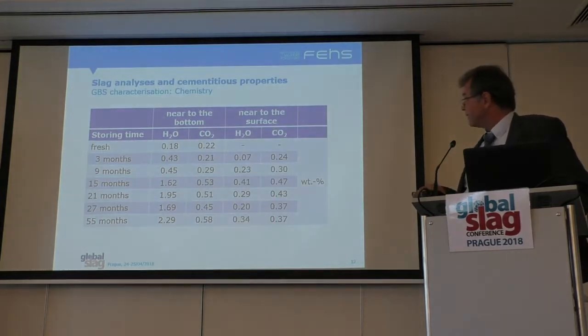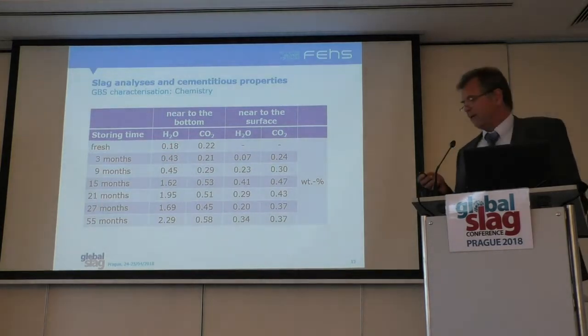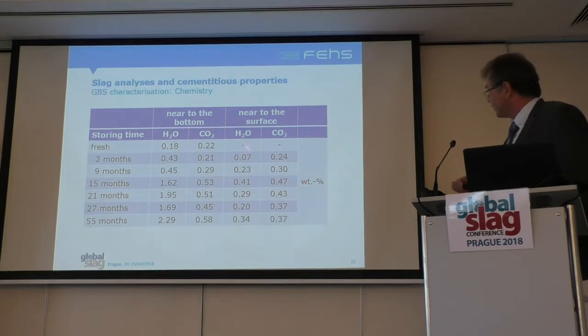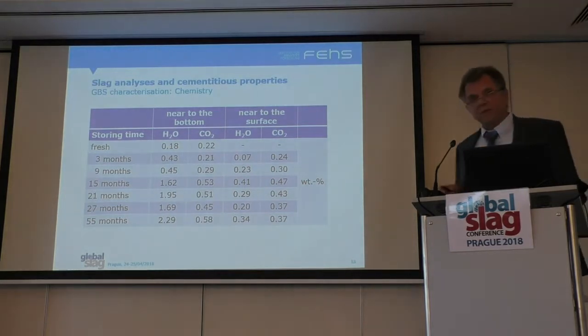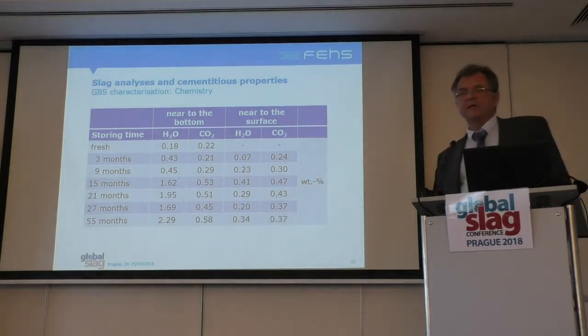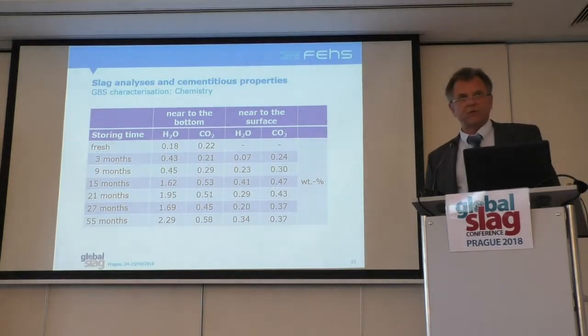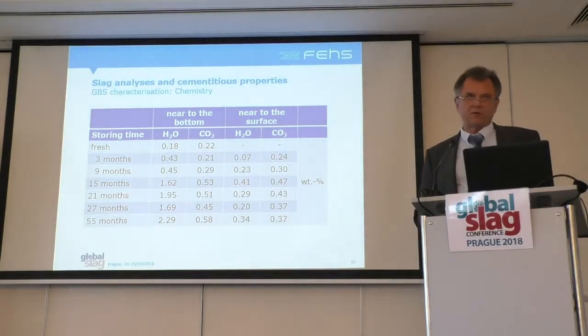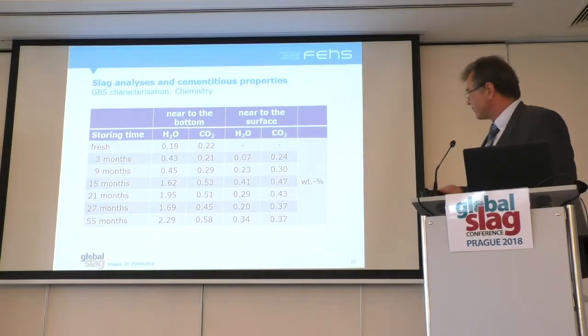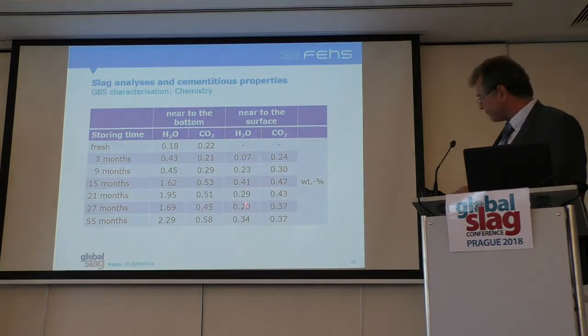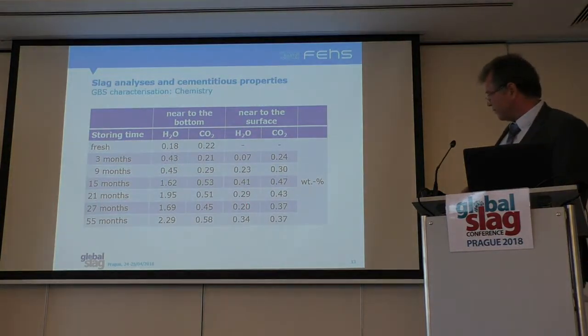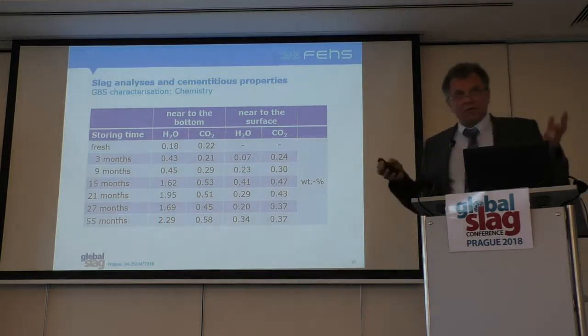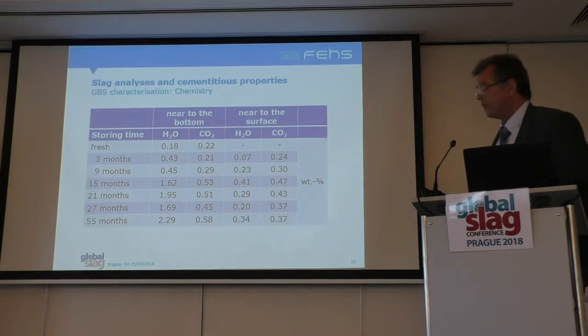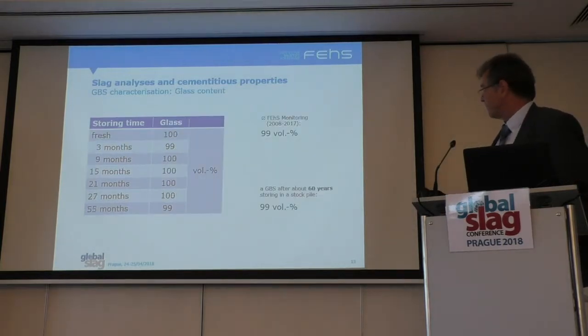That is regarding the sample taken from the bottom. The samples taken near the surface have a similar trend, but due to the storing conditions, dry, wet, hot, cold and so on, it's not so clear, and the chemical bound water and CO2 is not as high as it is for the main volume of the slag in the inside of the stockpile.